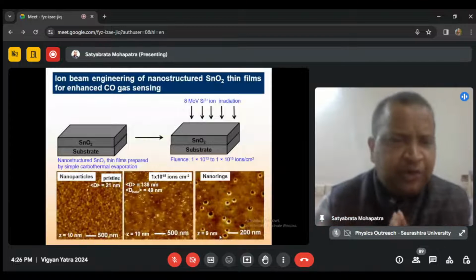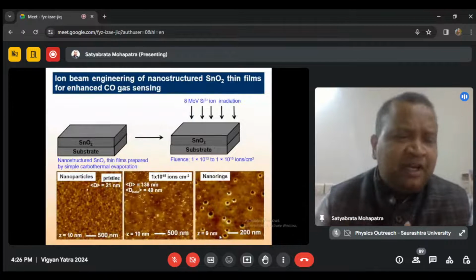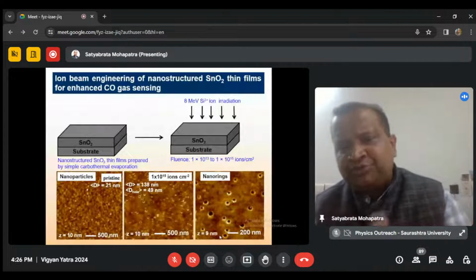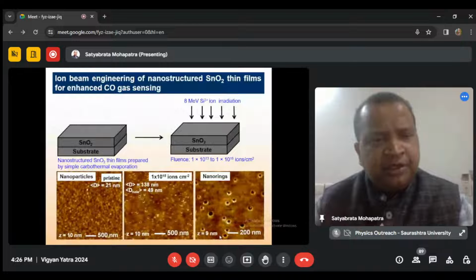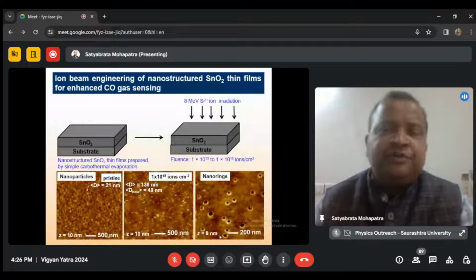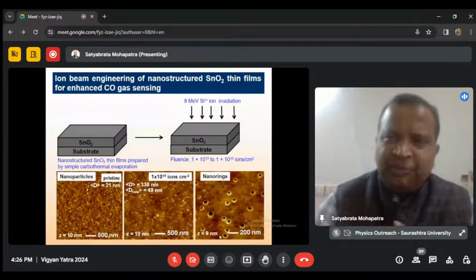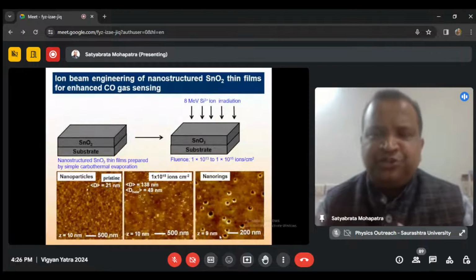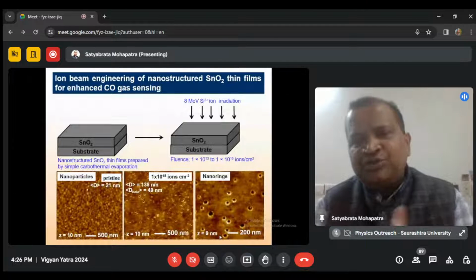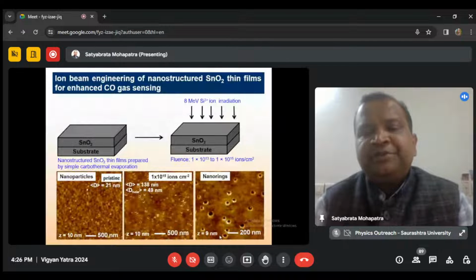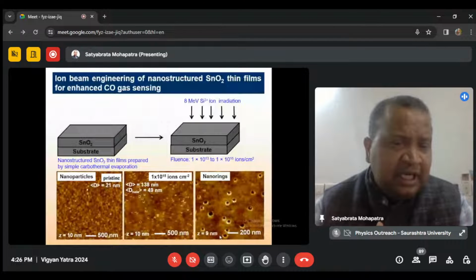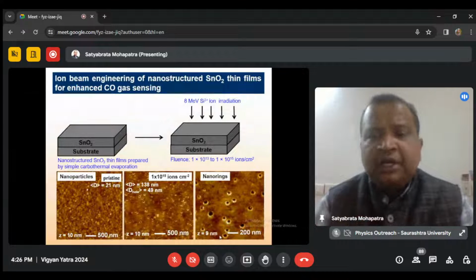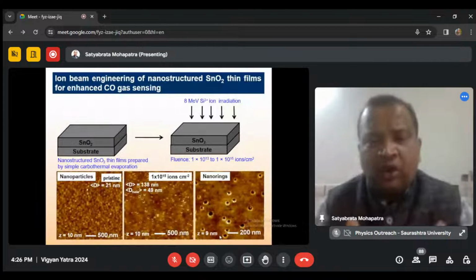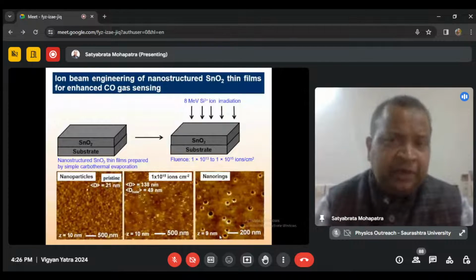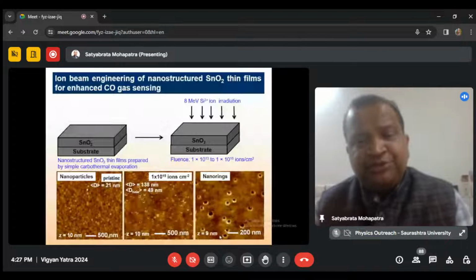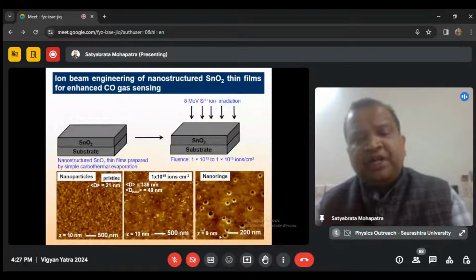So we took a very simple approach in which we deposited a 45 nanometer tin oxide film by simple carbothermal evaporation, the same film which we have shown earlier, and we irradiated these films coated on substrates using 8 MeV silicon 3+ ions from the 3 million volt tandem pelletron accelerator at the Institute of Physics, Bhubaneswar. The dose was varied from 1 × 10^13 ions per centimeter square to 1 × 10^15 ions per centimeter square, which is a relatively moderate dose. With the machine at Bhubaneswar, it doesn't take long. It's a pretty quick exposure, and that's it. So we have an engineered nanostructure film, which you can prepare very quickly, and just need evaporation and exposure for some time. That's it.